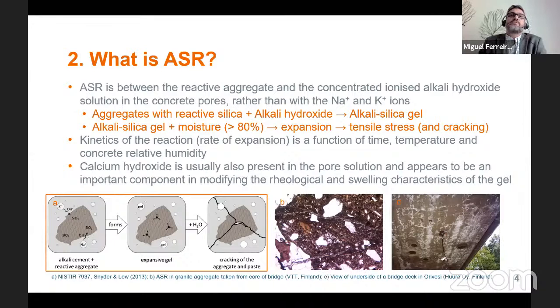Basically, it's a series of chemical reactions that occur within the concrete, and these involve three main parts. The first part is a reactive aggregate. This means some form of reactive silica, amorphous silica, and this is attacked by the second part, which is the hydroxyl ions, OH minus, that are present in the pore solution of the concrete. And these ions will help accelerate the dissolution of the silica, the amorphous or the affected silica in the aggregate. And the sodium and the potassium ions will keep the pH in the pore solution very high, and this helps keep the solubility of the silica at an adequate level. And of course, the last part of this reaction is the need for humidity or water, which will act as a solvent and also as a carrier for the hydroxyl and the alkali ions.